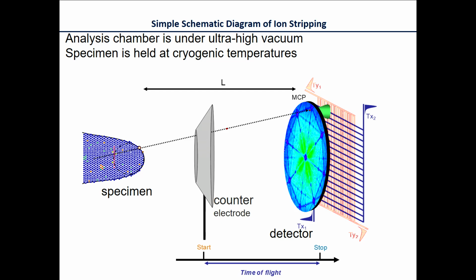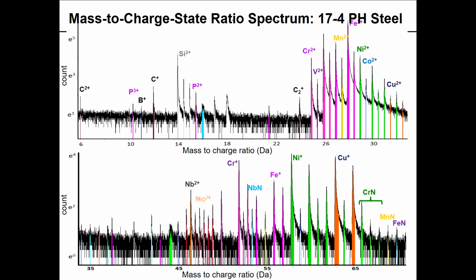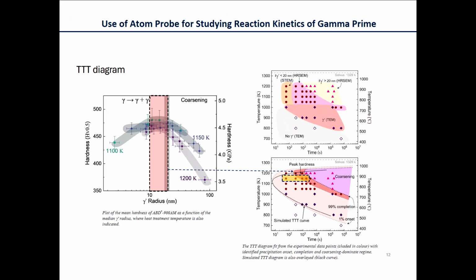Typically, what's done for the three-dimensional reconstruction is to have a counter electrode. We have also a gate here, a detector, and we measure the time of flight. And from the mass to charge ratio, we can work out which ion has been stripped away one by one. These days, it's quite possible to build up maps of maybe 100 million atoms using this kind of technology. Here's an example of a typical spectrum that you derive in that way. And you can see that each peak here has to be indexed with software for determining which ion is which.